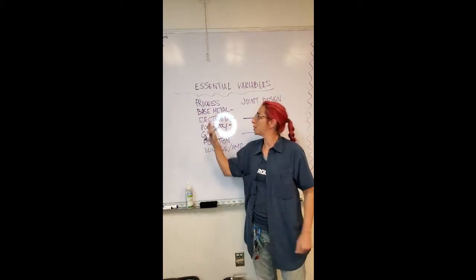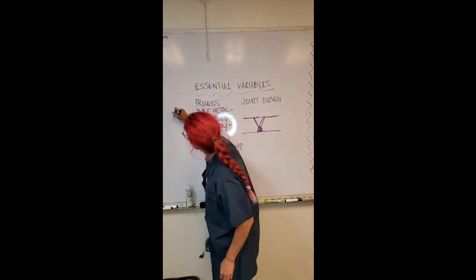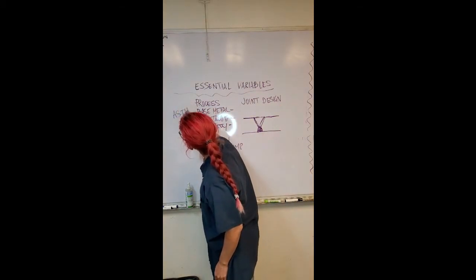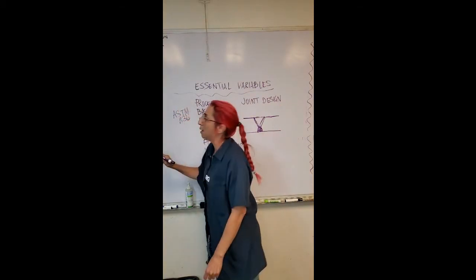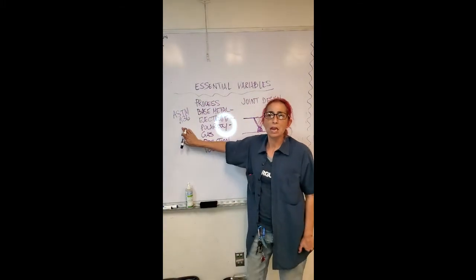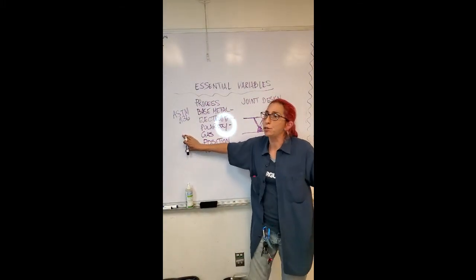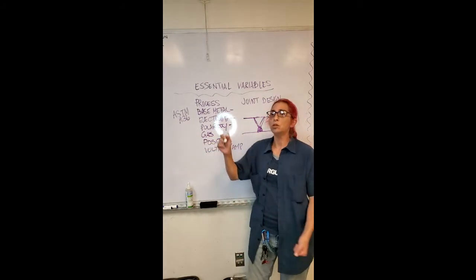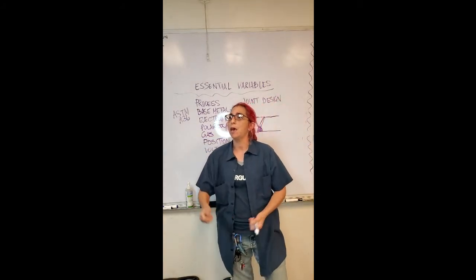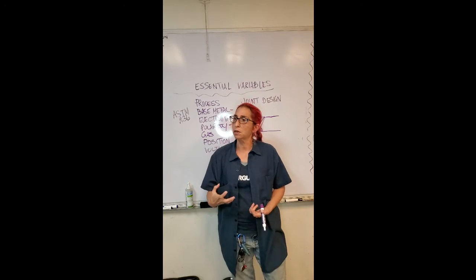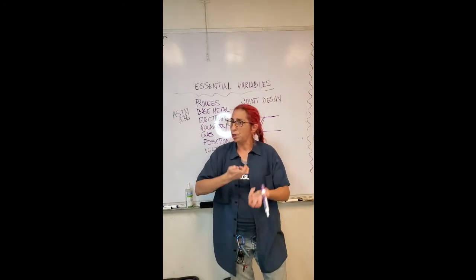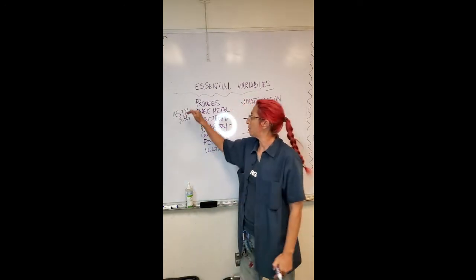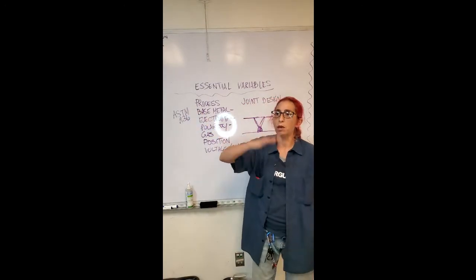Okay, so they give us an ability to change. So if this is a group metal, or a group 1 metal, which is ASTM A36, and I find one like A52, and it's still within that group, usually we don't have to qualify because they have the same characteristics. And there's minor changes. But if it falls outside of that group, then yes, we have to requalify.